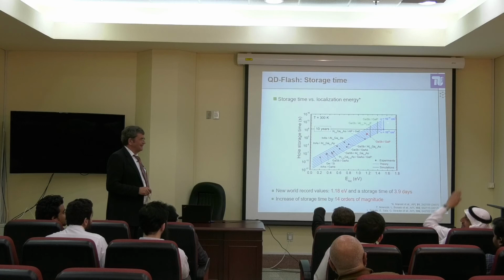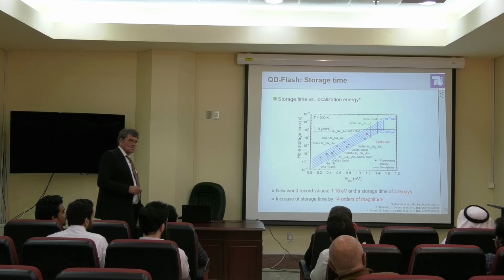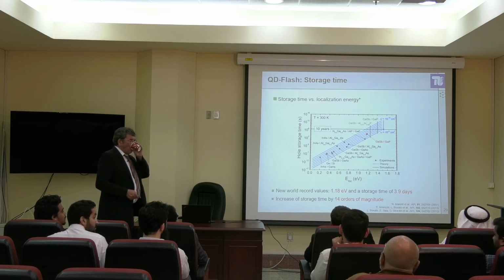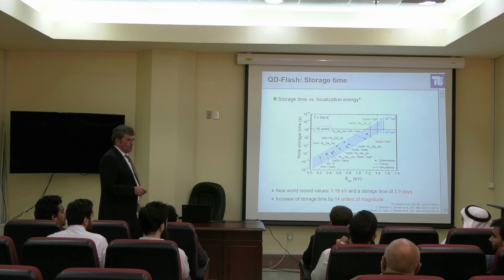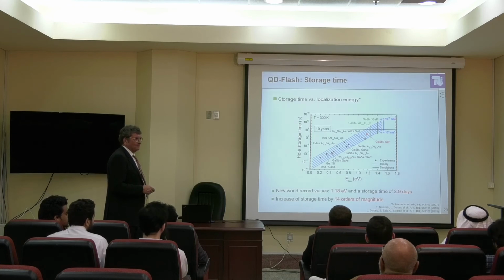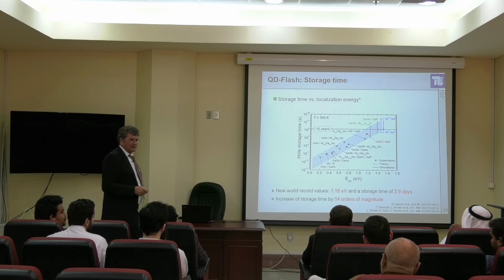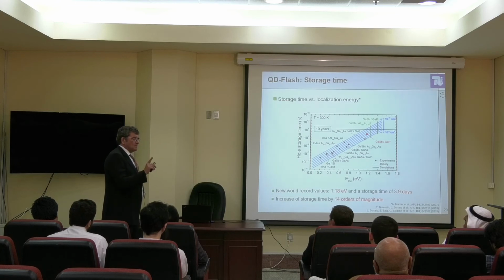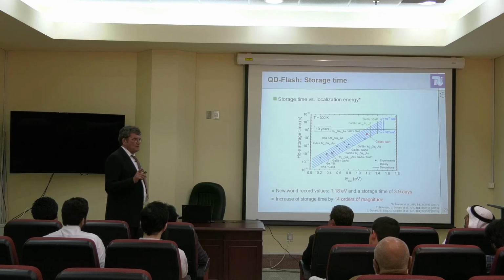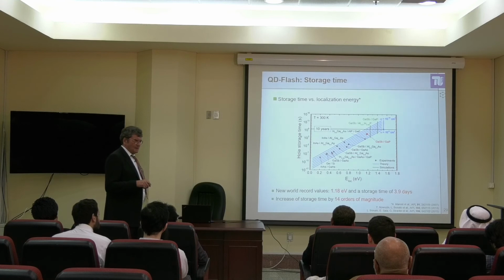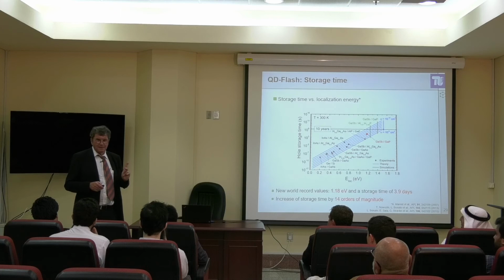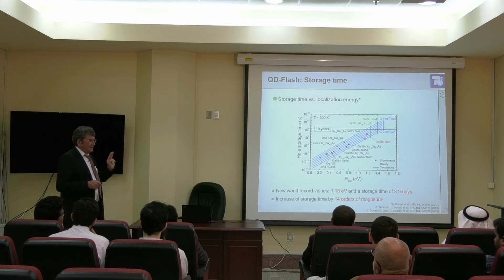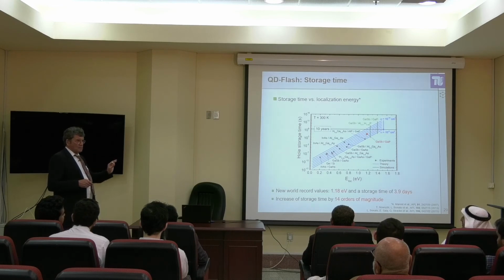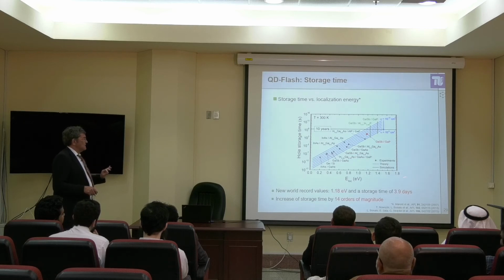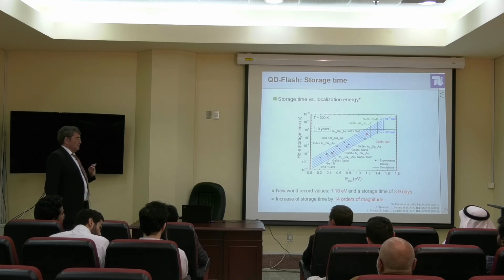No. Think about it. Look at the storage time. Which one do you want to have? This one. Less sigma. He's asking about sigma. And look, sigma of 10 to the minus 15 gives the longest storage time. Okay. You want to have small. So I was saying the capture cross-section goes with the size of the quantum dot. You want to have small quantum dots or large ones? Small ones. Now if the quantum dots are smaller, you can have also a higher density. So it's a double whopper. It's good. What you have to do is make small quantum dots, but with a large localization energy, and then you get at the same time a large storage time and a large density. That's what we're going to have.